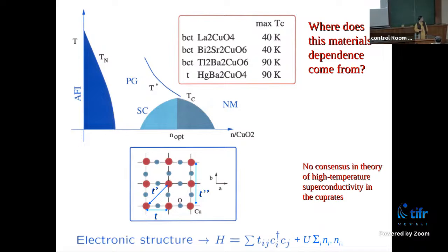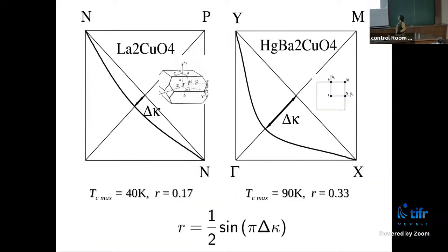It's more than twofold. So where does this material dependence come from? There must be a reason. We want to make TC higher and higher, so we should have an understanding. And clearly, this has almost nothing to do with the essential ingredient of the superconductivity, because if you believe copper oxygen is doing this superconductivity, then it is the same for all of these compounds. Well and good. This is basically the Fermi surface.